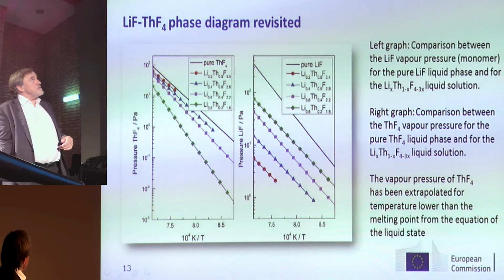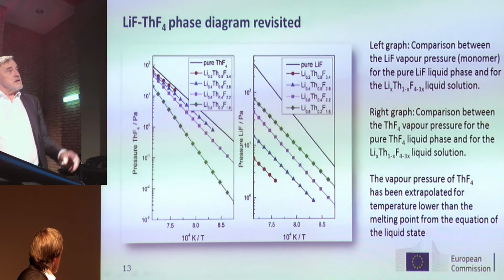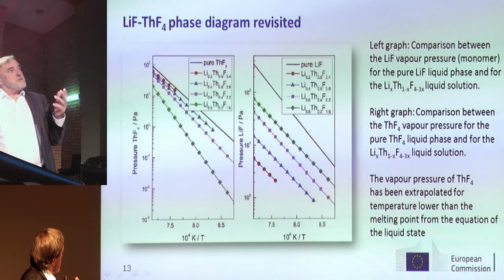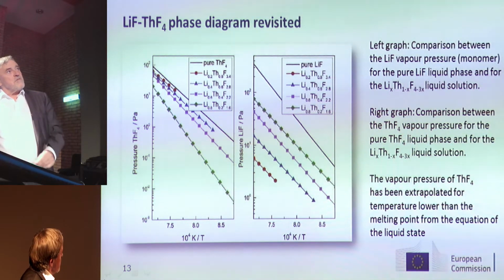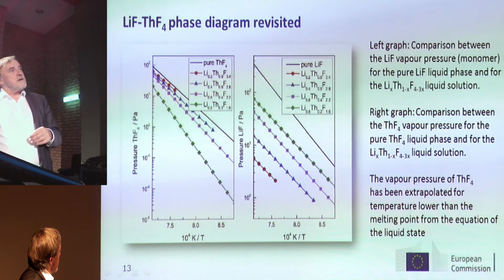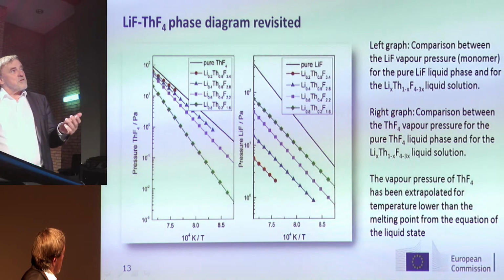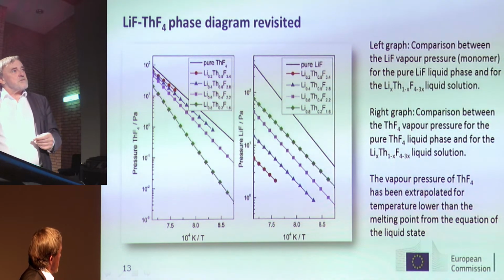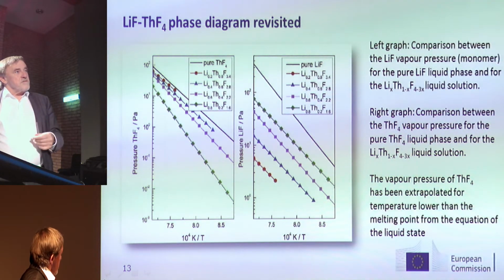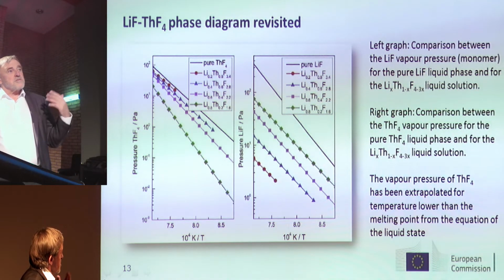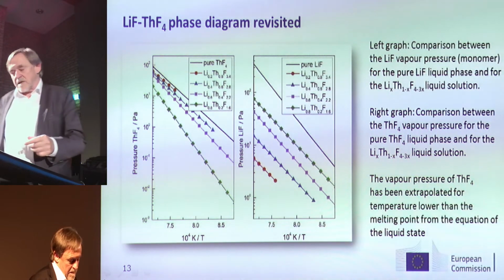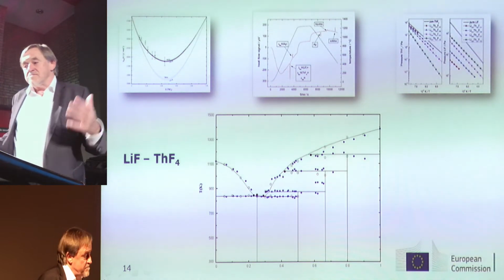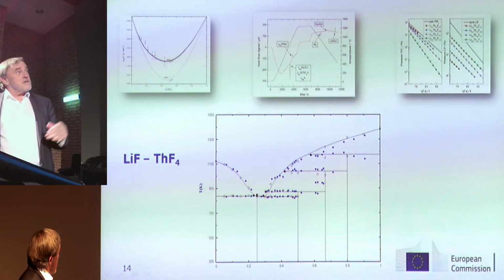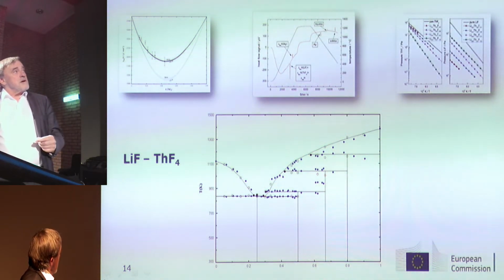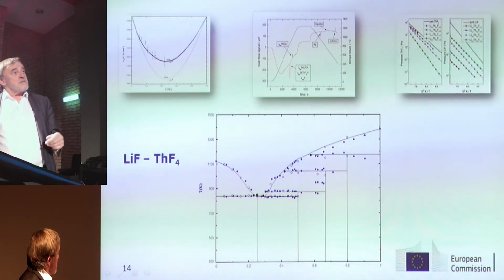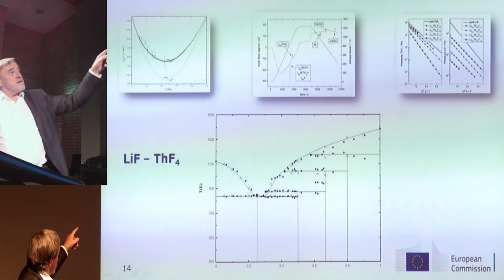Then we have also revisited this phase diagram of lithium fluoride and thorium fluoride. So you see here two graphs, where the left one is the comparison between the lithium vapor pressure as a monomer for the pure lithium fluoride liquid phase, and for different mixtures as a liquid solution. And on the right side is the comparison between the thorium fluoride and, again, the different compositions between lithium and thorium fluoride in liquid solution. And the vapor pressure for the thorium has been extrapolated also for temperatures which were lower than the melting point of the equation of the liquid state. And then all these data that were produced by the different techniques were assembled to give the final phase diagram that you see on this view graph. So you see the different techniques, and then the final result, the experimental data and the calculation of this result for the system lithium fluoride, thorium fluoride.